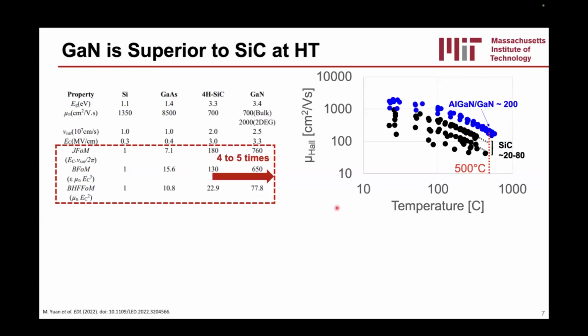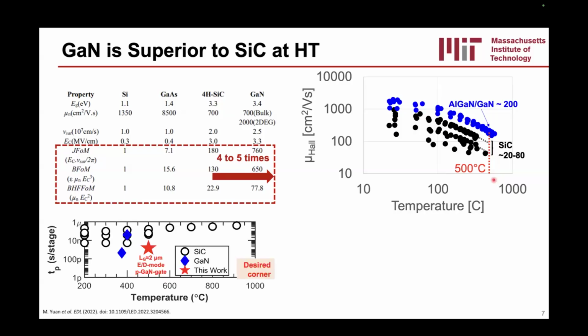If you look at, for instance, the Hall mobility versus temperature for silicon carbide devices, as you can see in black here, and AlGaN GaN devices, as you see in blue here, you can kind of see the AlGaN ones are always higher, even across the whole temperature range. And if you extrapolate to 500 Celsius, the AlGaN GaN devices typically have a Hall mobility of about 200 centimeters squared per volt-second, while the silicon carbide devices have about 20 to 80 at most. And once again, this is the Hall mobility, not the field effect mobility, which for silicon carbide devices can be considerably lower. And we see this in practice too.